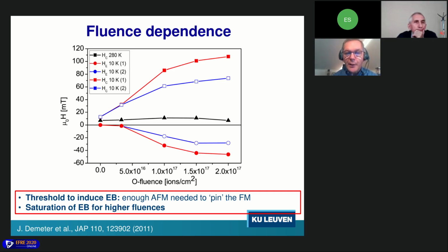And what you see here is that you need a minimum amount of oxygen before exchange bias appears, and that it then saturates at higher fluences. So what this actually means is that you simply have to create a minimal amount of cobalt oxide before you can start to pin the ferromagnetic layer.